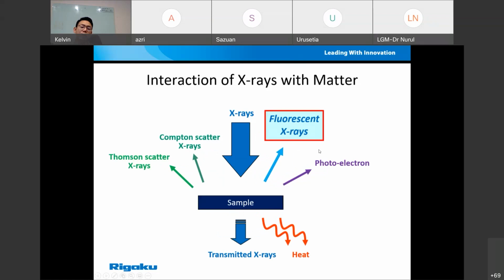When the X-ray hits the sample itself, it is not only generating the fluorescent X-ray. This is what we use for the WDXRF analysis, and EDXRF also uses this as one of the things to analyze. We also have a lot of photoelectron effect. Most of the X-ray is converted into heat. That's why when you use WDXRF or any X-ray technology to measure a sample, it is going to heat up the sample. And there is also some X-ray which transmits through the sample.